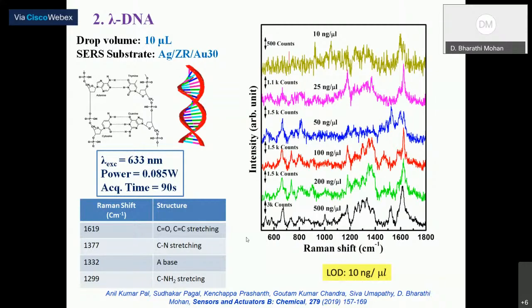We prepared DNA with different concentrations ranging from 500 nanogram per microliter to 10 nanogram per microliter. And you can see that Raman spectra is obtained up to the concentration of 10 nanogram per microliter, which means the limit of detection is up to 10 nanogram per microliter for the case of gold zinc oxide hybrid nanostructure.